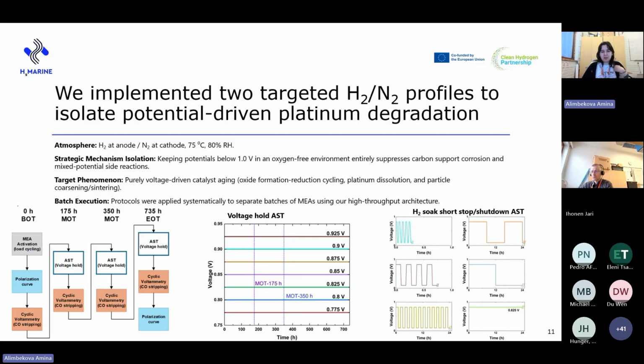Using this approach, we have developed these 2 distinct AST protocols that were applied for 2 different separate batches of MEAs. Here you can see the AST sequence for voltage hold, where we have mimicked the long steady state runs at different voltage values. And this is to track the catalyst degradation under constant voltage stress.